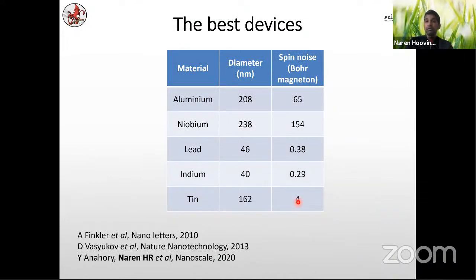So this is just a table of the different materials that were used at the time I was working there. You can see that there are some devices made of, say, lead and indium, which are so sensitive that their spin sensitivity is much better than 1 Bohr magneton. So in principle, if we can isolate a single spin, which is a challenge by itself, this device can actually detect it. So that was a cool achievement of these devices.